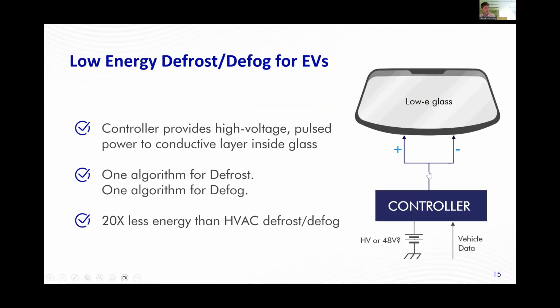So the current ways of transferring heat, you have all these heat transfers, you have it all directed to a very concentrated place on the glass, so the heat is not evenly distributed. It's just very inefficient. And so using that transparent metal layer that's in the glass to be the source, you get this even source of heating that can defrost FMVSS 103 in 1 minute. And so the controller that we develop is connected to bus bars that are in the windshield. We have one algorithm for defrost and one for defog, and this uses about 20 times less energy than an HVAC system.